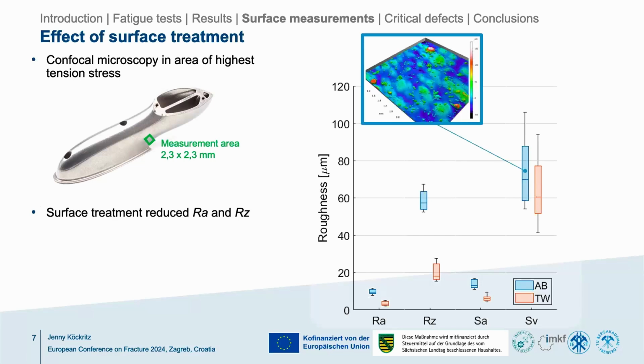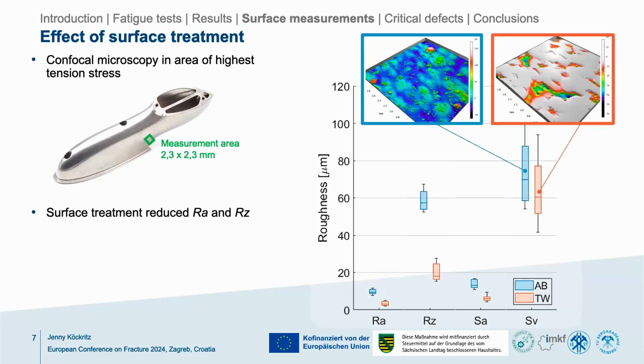If we look at the topography of the as-built specimen, we see kind of a bumpy surface with some baked-on particles, some valleys, some peaks. And if we look at the topography of the trovalized ones, we see that the surface treatment was actually able to take off all the peaks, but wasn't able to reduce the valleys at all, which are the detrimental effect for fatigue in the end.